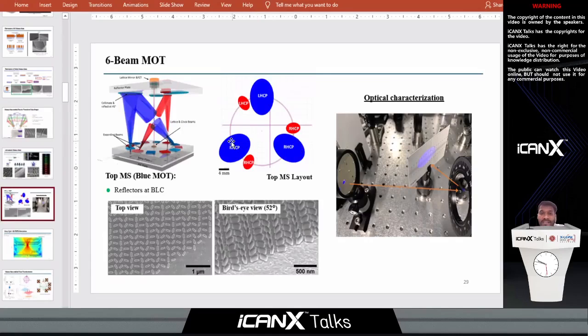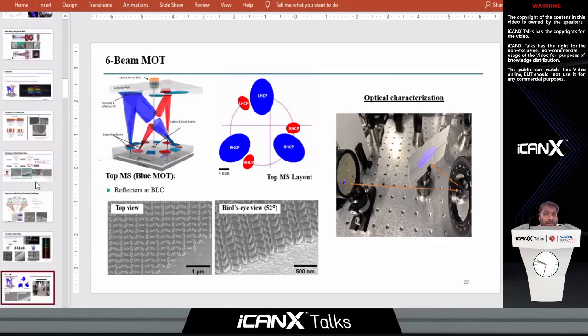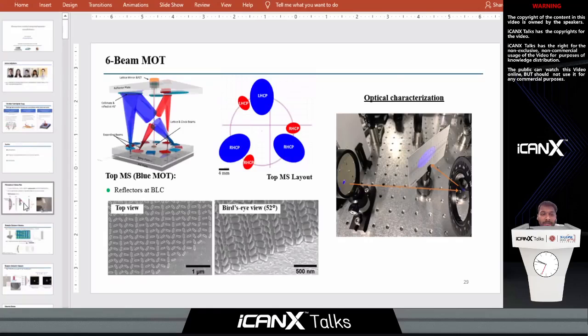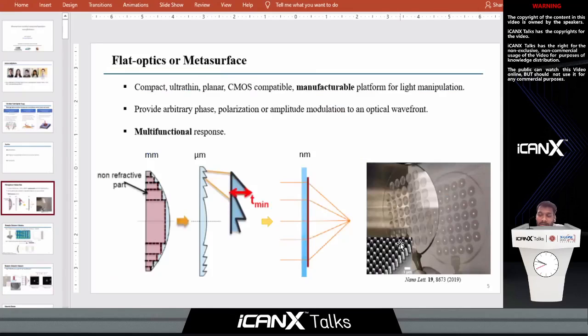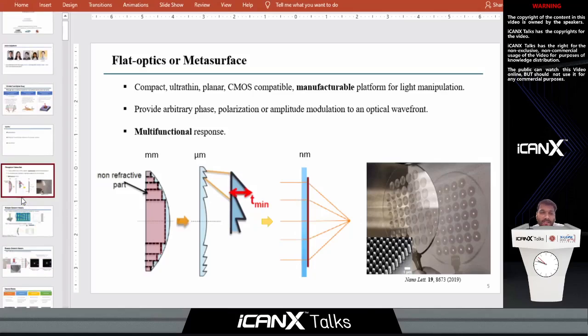So the challenge is really trying to come up with an approach where maybe instead of e-beam, they can be fabricated using deep UV stepper lithography, right? And so stepper is right at the limit of where they can give you certain functionalities, but if all of these devices can be made using deep UV, then that's the way to go. E-beam is great, but it is a serial process at the end, right? But we can make centimeter scale metasurfaces as overnight writing, or say a writing over like 10 to 12 hours. Okay. Thank you.